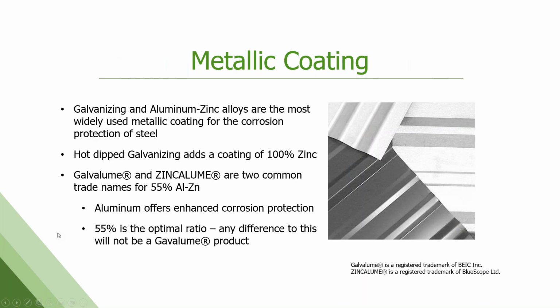So before we dive more into paint, though, I do want to talk a little bit about the substrate underneath, because it is a very important part of the whole package here. So most coated steel is either galvanized, hot dip galvanized, or an aluminum zinc alloy, the most common being Galvalume or Zincalume, the two trade names you might see out there in the market. That's a 55% aluminum zinc mixture. When you add aluminum in with the zinc, you get enhanced corrosion protection and performance long-term versus straight hot dip galvanized, which is 100% zinc.